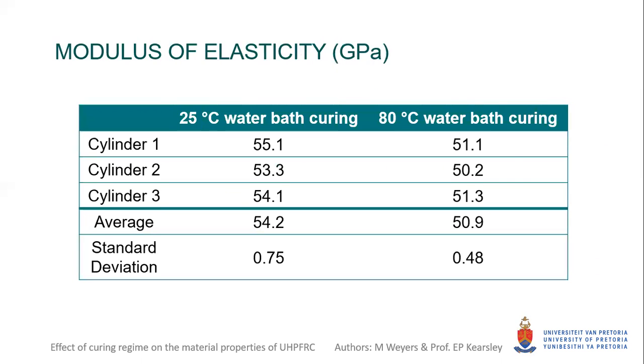The modulus of elasticity results are shown in the table. The cylinders cured in the 80 degrees Celsius water yielded a slightly lower value compared to the cylinders cured in the 25 degrees Celsius water. However, a low standard deviation was obtained for both curing regimes.